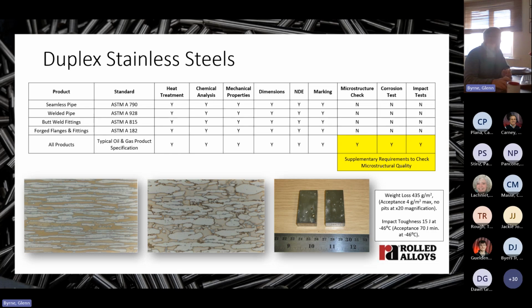We don't know there's anything wrong with the steel until something bad happens, like it corrodes or it cracks. So we use metallurgical examination of polished and etched sections, like you see here, and toughness and corrosion testing to confirm freedom from these deleterious phases on a cast and batch basis.